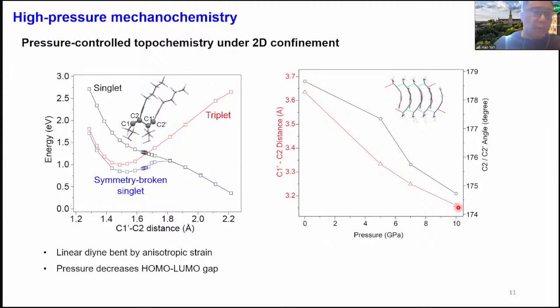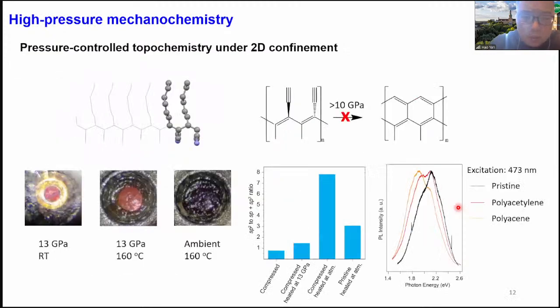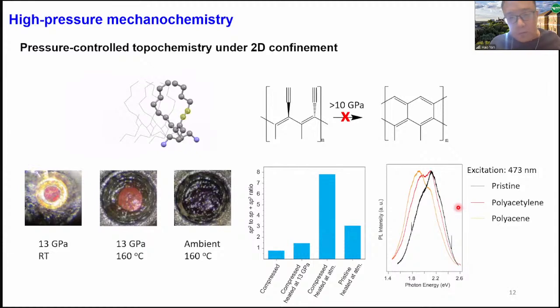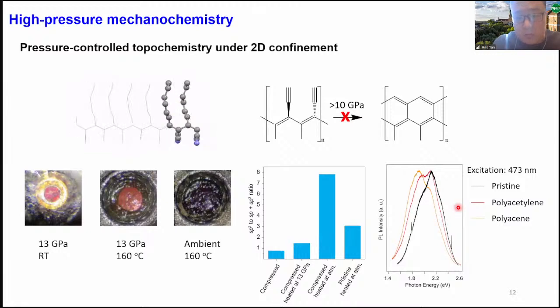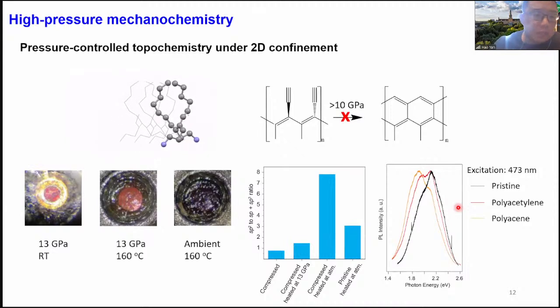That's item number one. Number two, now once these polyacetylene molecules form, we still have half of the triple bonds that are not reacted, and in principle, they can react and undergo another step of polymerization, forming a polyacene, or a single-file graphene nanoribbon, if you will. What we see is that this reaction does not happen under high pressure.